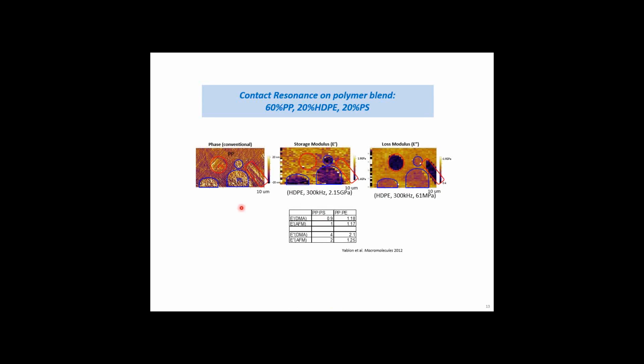So by tracking that Q and frequency and applying the appropriate models, you can get images such as the one shown here. This is a blend of 3 polymers: polypropylene, polystyrene, and polyethylene. You can see that the phase image actually shows very little contrast between these 3 materials. But when we conduct contact resonance to measure the storage modulus and the loss modulus, we get very nice differentiation between the materials in these maps. And you can note that the Z scale is now in units of gigapascals, actual modulus units.